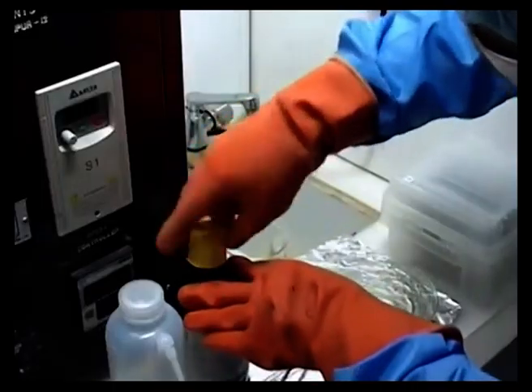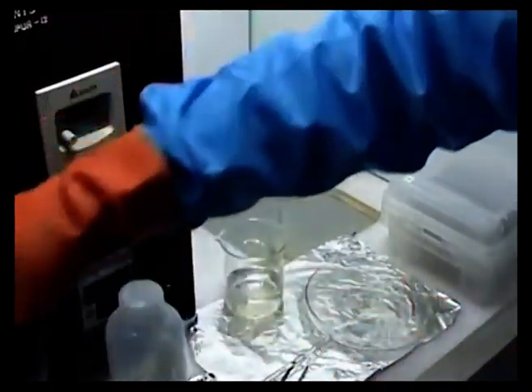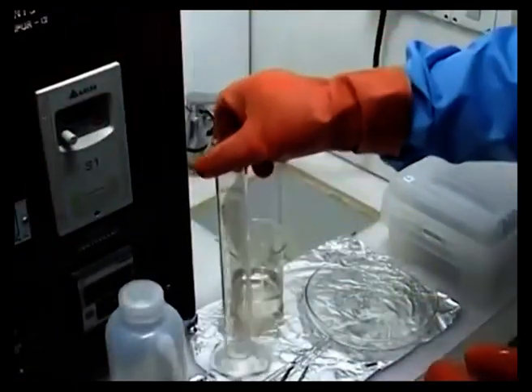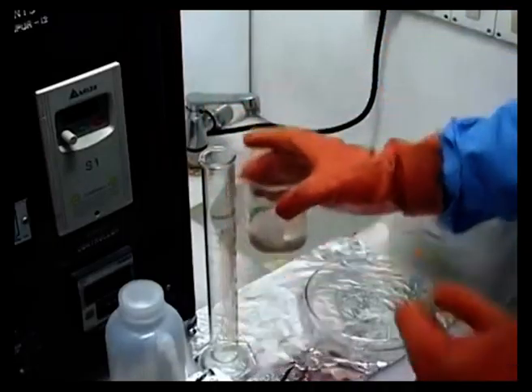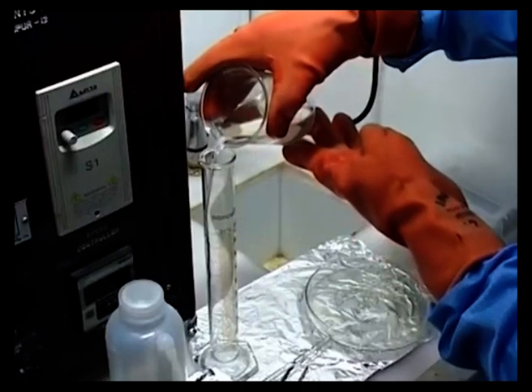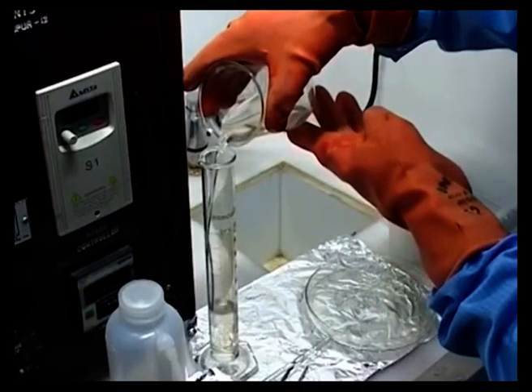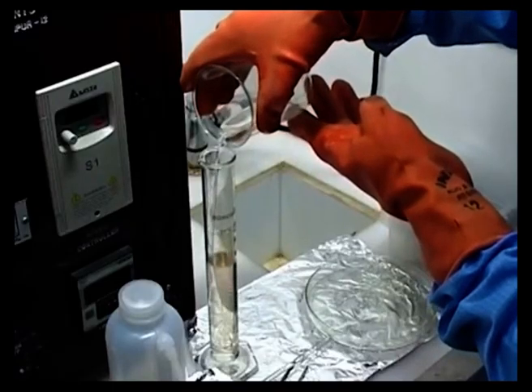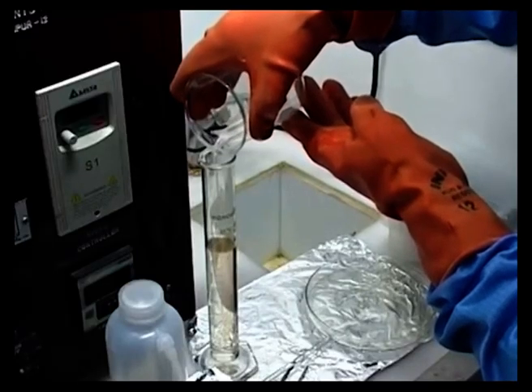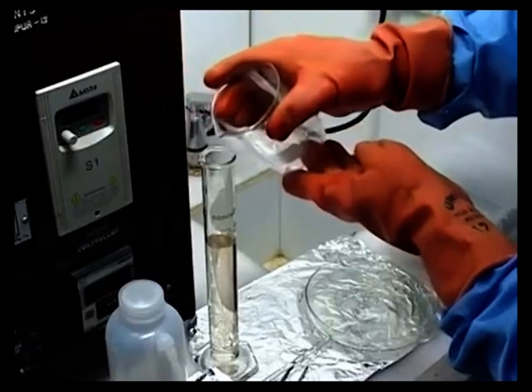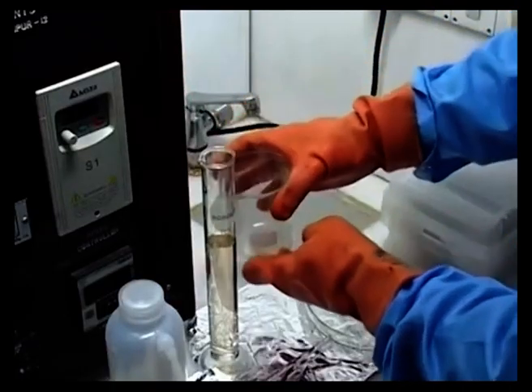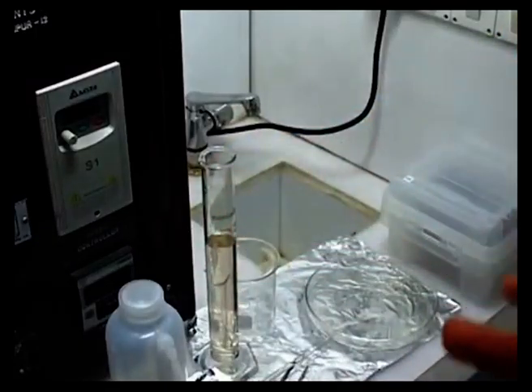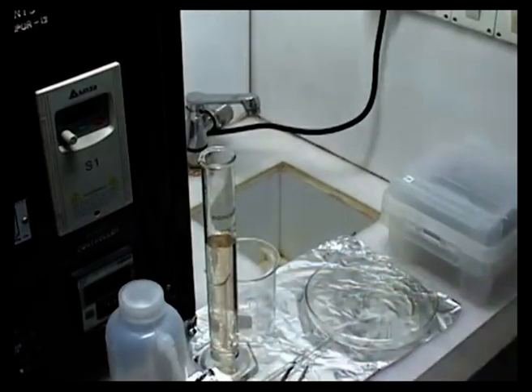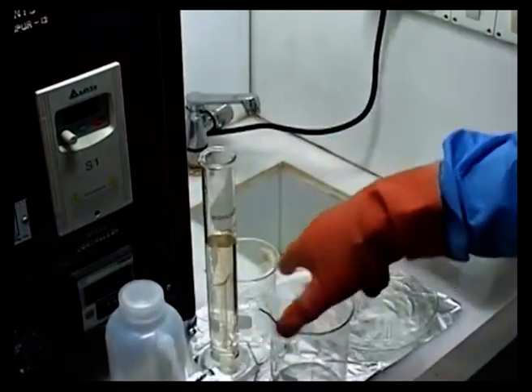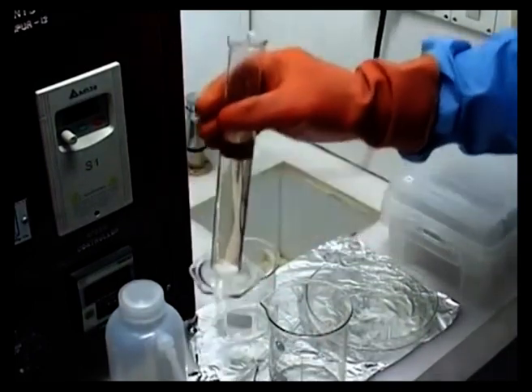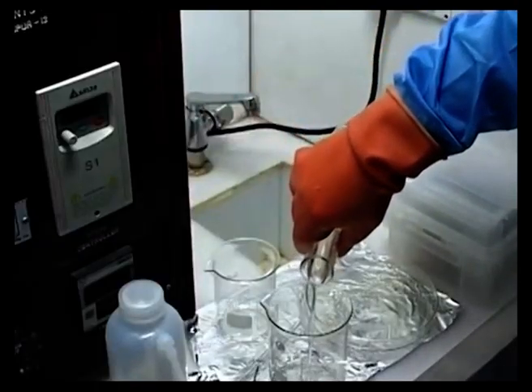Okay, and we need to actually do a secondary measurement to ensure that the volume that you are using is proper. So use a measuring cylinder for that, and we need to pour exactly 90 ml here. So what we'll do is transfer this sulfuric acid into this measuring cylinder and go all the way up to 90 ml. Which is just about complete now. So we take a new container in which we have to prepare the piranha and slowly pour from the measuring cylinder the sulfuric acid.